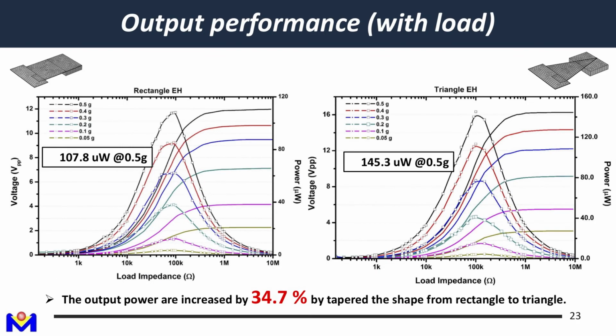Okay, so this is some testing of the microcantilever with different load impedance, and this is the voltage output and power output on this axis. And you can see for rectangular, we can generate about 0.5 G at around 100 microwatts. And for the triangular one, at the same acceleration level, we can reach around 145. So it's increased about 34.7%.